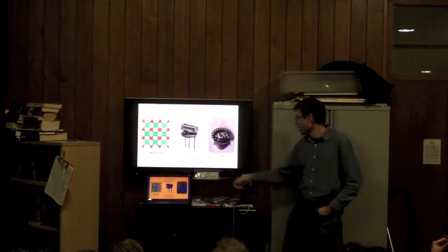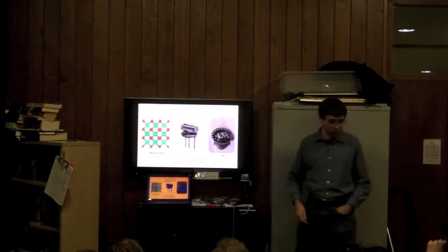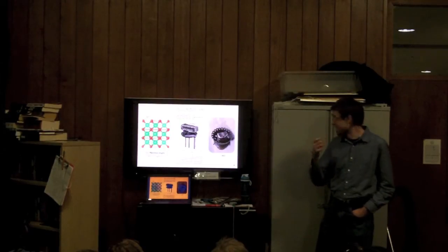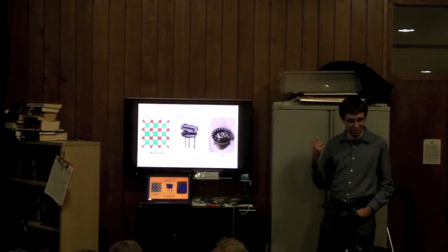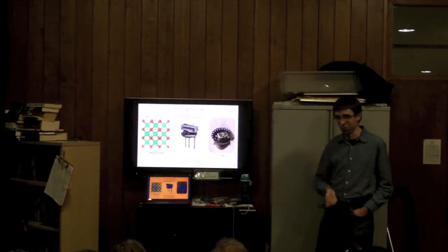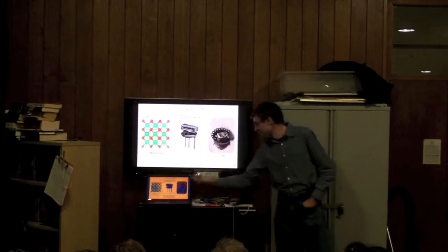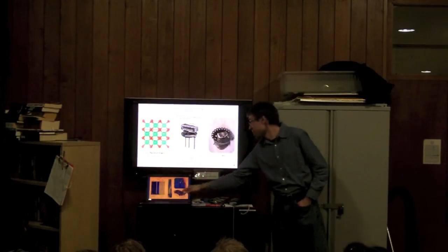And then they found out, oh, actually, it's not feasible to heat them to 500 Celsius every time. Because every time you turn on the light, you have to heat it up to this temperature. And then when you want to turn off the light, you have to cool it back down. So no, this didn't work. But we still managed to use this technology.